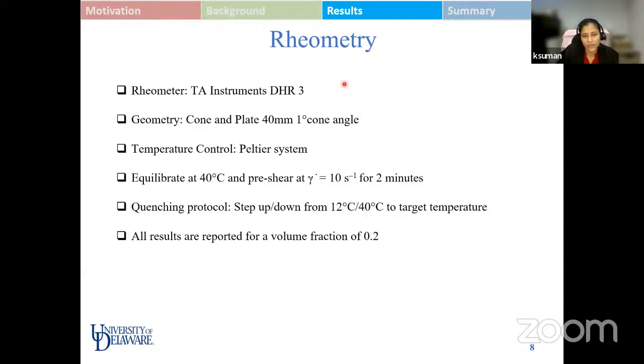A brief look at details of how we do the experiments. We have a TA Instruments DHR3 rheometer, and we use the cone and plate geometry with 40 mm diameter and 1 degree cone angle. We have temperature control using the Peltier system, which gives very precise control in temperature up to 200 degrees centigrade. Since this is a thermoreversible gel, it is very convenient to pre-shear the sample by taking it to 40 degrees, which is a liquid state for this gel, and we pre-shear it for 2 minutes at a high shear rate. We then apply the quenching protocol, which is giving a step change in temperature from the initial temperature, and study the rheological behavior. All the results I'm going to report here are for a fixed volume fraction of 0.2.